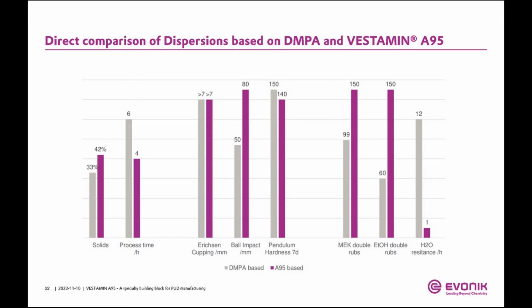What we have to admit, of course, at this point, and we cannot avoid it, or we should mention it in any case, the water resistance of the A95 is significantly lowered. If you use a system that has a high content of A95 and you choose to go for high solids, you will have a reduced water resistance of your dispersion.